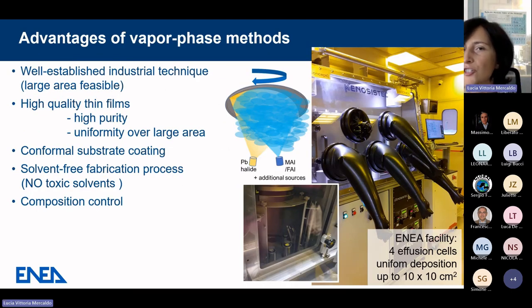So what are the advantages of vapor phase methods? Evaporation is a well-established industrial technique where large area is feasible, as it has already been demonstrated. It is possible to obtain high quality films with high purity and uniformity over large area. It is possible to obtain conformal substrate coating. So in case we have texturing, you really have a conformal coating.